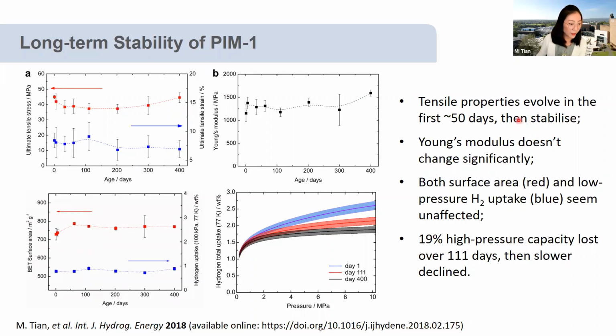And finally, we need to know the long-term stability of PIM1, because the general problem for polymers is degradation. The polymer is really easy to degrade, to age. So to evaluate its long-term stability, we carried out this 400 days work. We keep the material and test its mechanical property and other properties over 400 days. And interestingly, we found those polymer chains are kind of flexible, and they are rearranging and relaxing in the first 50 days. And then they stabilize, like fine wine.